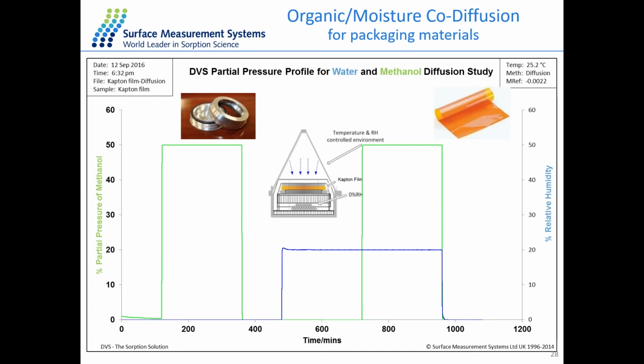So what we get from the result is, with the methanol only diffusion for the first stage, the diffusion coefficients we calculated are quite similar to each other. So temperature has very little impact on the methanol diffusion in this case. But temperature has a huge impact on the water diffusion, which we calculated for the water only stage. And for the last stage, with the presence of water, the diffusion rate of methanol also improved at higher temperature, where we got the diffusion rates at 2 different temperatures. So that's how we measure the temperature factor as well as the background humidity factor on the diffusion rate for the packaging material.